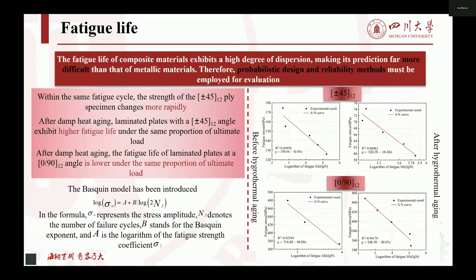Due to the high dispersion of fatigue life exhibited by composite materials, this study explores probabilistic design and reliability methods for evaluation. Using the basic model for fatigue life prediction, the red S-N curve indicates that after hygrothermal aging, the 45-degree laminated board exhibits a higher fatigue life under the same load ratio. However, the fatigue life of 90-degree laminated boards is relatively low.